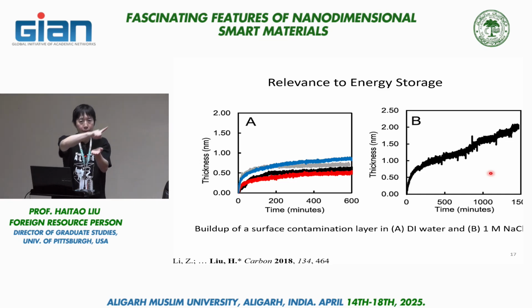And then I analyze the reflected laser light. By analyzing the polarization change and the intensity change, I can figure out how much additional thin film is being grown at the liquid-solid interface. So same experiment, except yesterday I was showing the growth of thin film at the air-solid interface. Now I'm looking at the liquid-solid interface.